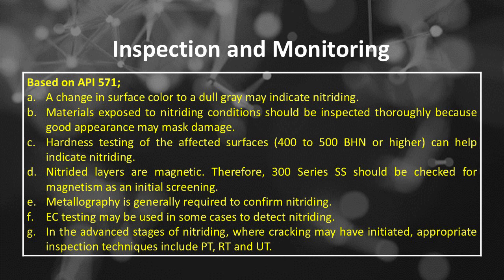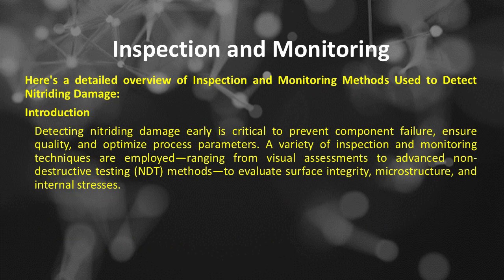Number E, metallography is generally required to confirm nitriding. Number F, EC testing may be used in some cases to detect nitriding. Number G, in the advanced stages of nitriding, where cracking may have initiated, appropriate inspection techniques include PT, RT, and UT. Here's a detailed overview of inspection and monitoring methods used to detect nitriding damage.